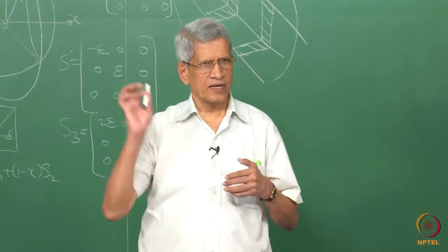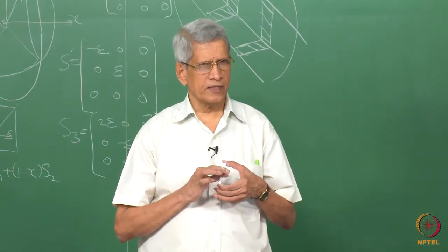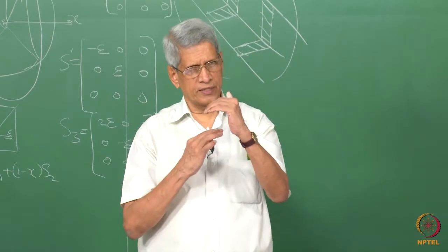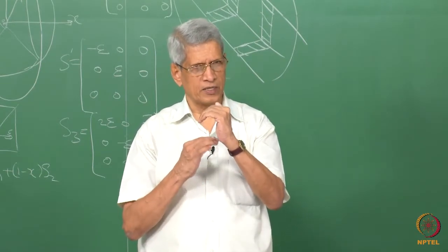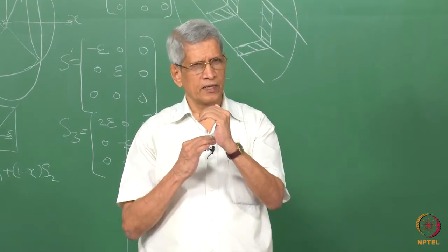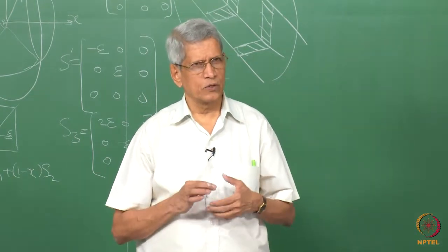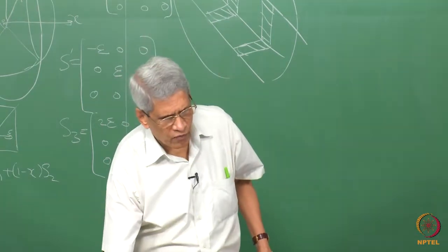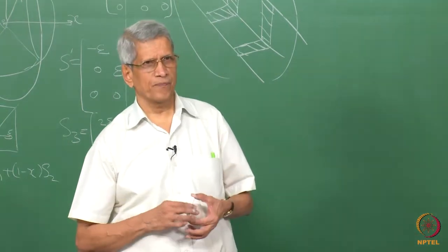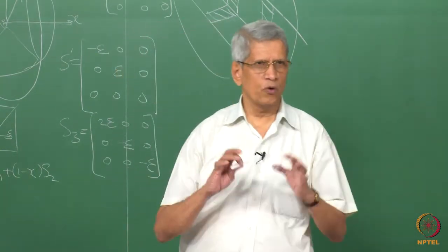The carbon gets stuck at different positions. That changes the unit cell along whichever direction the carbon is stuck in. There is a slight tetragonal distortion, so it becomes a body centered tetragonal structure. Correct. So here, as I mentioned, how do we go about